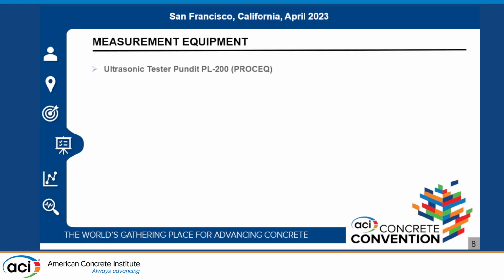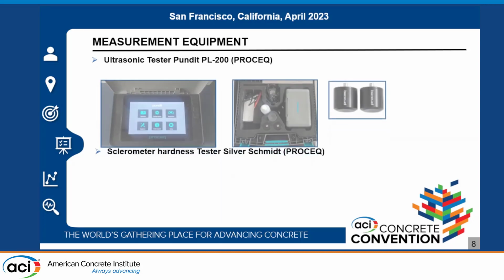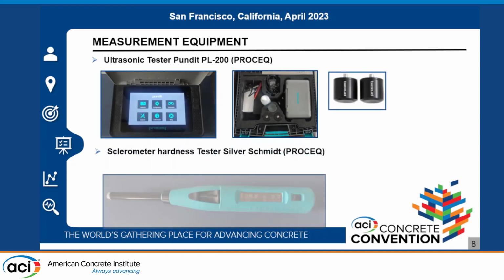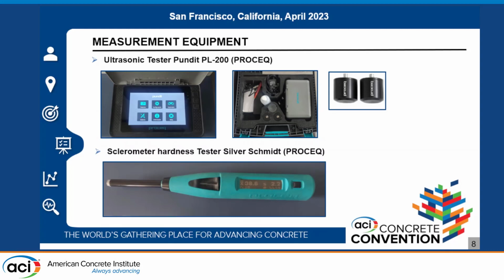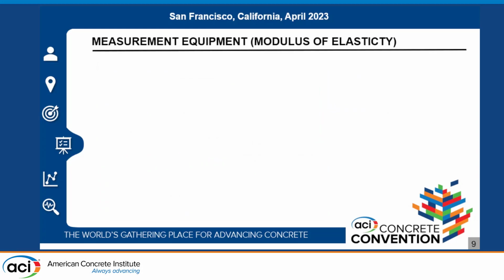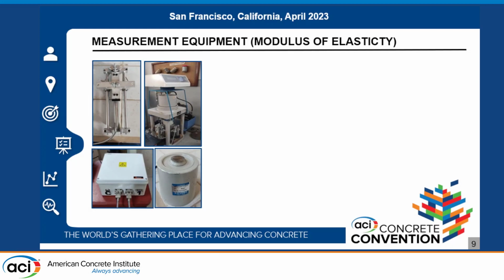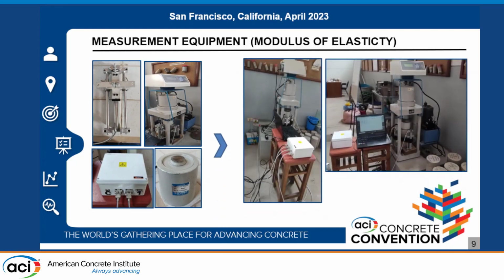The measurement equipment used to read the ultrasonic pulse wave was the ultrasonic tester Pundit PL200 from Proceq brand, and to read the rebound index was the Sclerometer Silver Schmidt tester, also from Proceq brand. Finally, the measurement equipment used to read the modulus of elasticity consisted of a data logger, three encoders that record the unit strains, and a load cell in charge of recording the force applied by the loading press. Here you can see all the equipment assembled.